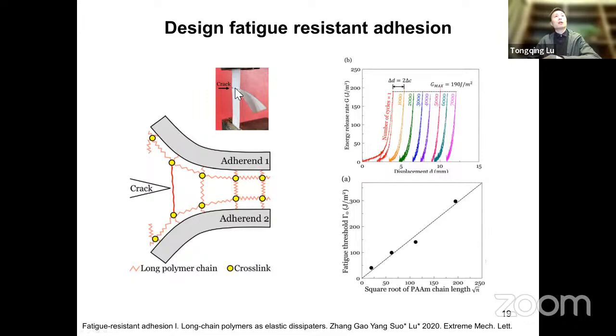Yeah, four kinds of PAAm hydrogels as the interfacial adherend. So we measure the fatigue threshold of this interface. We can see it also follows this theoretical prediction, proportional to the square root of the chain length. And by simply increasing the chain length of this hydrogel, the fatigue threshold of the interface can be increased from maybe 50 to 300. It's a simple way to increase the fatigue threshold of the interface.